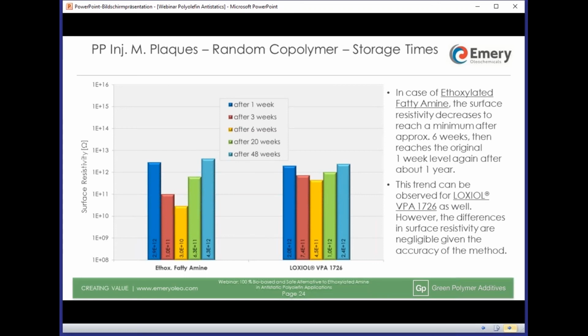Honestly, we had expected the plaques to require some more storage and so migration time to provide a decent antistatic effect, as the plaques are much thicker than the films, 3 millimeters versus 30 microns. However, this is not the case. Even the plaques that were tested after 1 week, plus 48 hours in standard climate, are more or less on the final level. Our explanation is that in injection molding, the polymer is kept molten without strong friction for a few seconds, and the additive has the chance to migrate in this state a lot more quickly than in solid state. In comparison with injection molding, the film in extrusion is cooled down more rapidly, so migration needs to take place mainly in solid state.